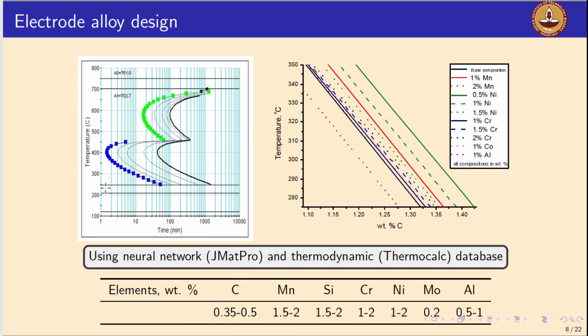Right, so for these identified chemistries, the important factors are that the martensite start temperature should be as low as possible, and the bainitic transformation should be as fast as possible. So therefore, by holding for a shorter time duration, we can achieve the isothermal bainitic transformation, what I described in earlier slides. Like for example, the candidate chemistry you see over here. So even if you are cooling at a very slow cooling rate, we may transform primarily to the bainitic microstructure. Right? If you are, for example, holding at 400 degrees centigrade, the transformation can be completed in about 100 minutes or so based on the CCT prediction.